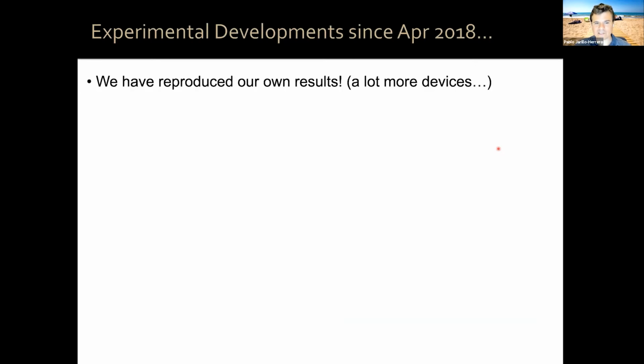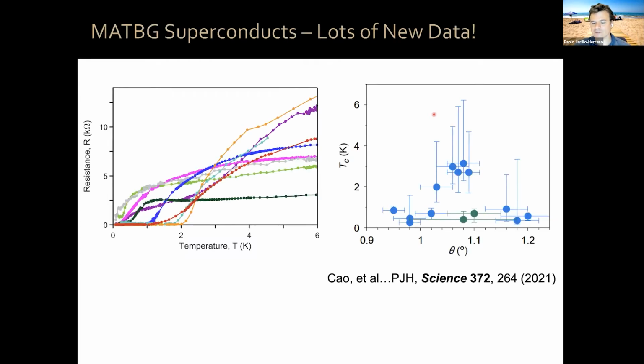Now, we published our paper officially in April 2018. We announced a month earlier at the APS March meeting. So what has happened since then? Well, the first thing that has happened is that we have reproduced our own results many times. Believe it or not, that doesn't always happen. So it's good that you're able to reproduce yourself. So by now we have dozens and dozens of devices. In fact, we're starting to map what is the critical temperature at optimal doping as a function of twist angle. This is a new tuning knob, okay, in condensed matter physics, the twist angle between two heterostructures.